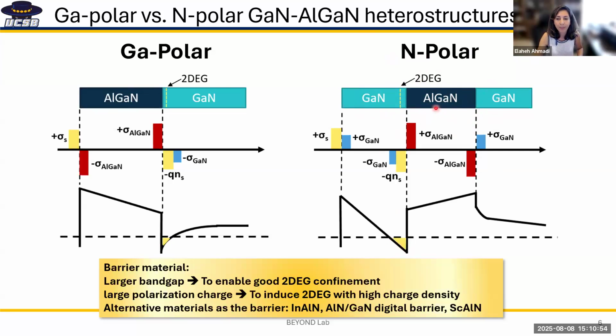This is true for both gallium polar and nitrogen polar: you would want a large bandgap material for the barrier for charge 2DEG confinement. We are interested in large polarization charge so that we can get larger 2DEG density. So as I said, in this schematic I'm showing AlGaN, but we can replace this with indium aluminum nitride, aluminum nitride, gallium nitride digital barrier that I'm going to talk about, and also scandium nitride that we are working on.